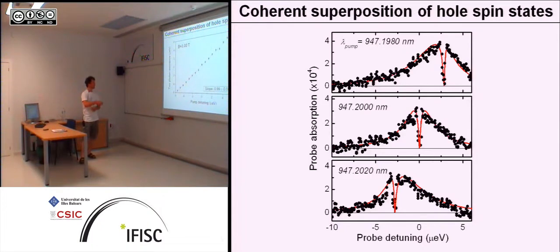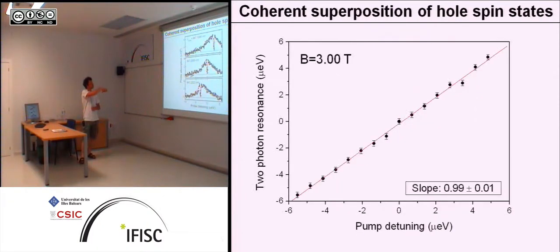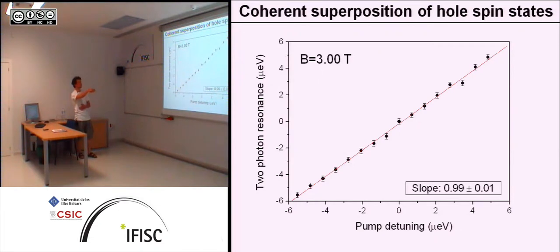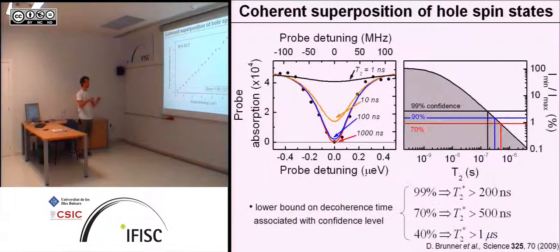So this is the position of this dip of the dark state plotted against the detuning of the pump laser. And you can see that it basically follows perfectly what you would expect in theory, a slope of 1, and here you basically get slope 1.